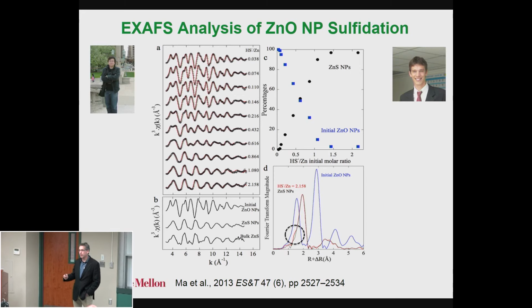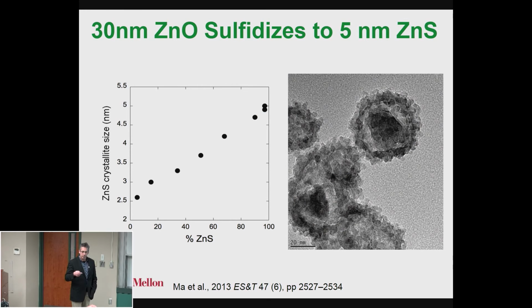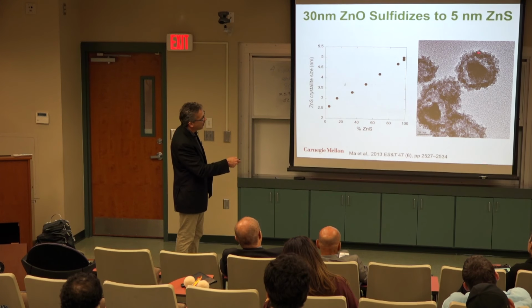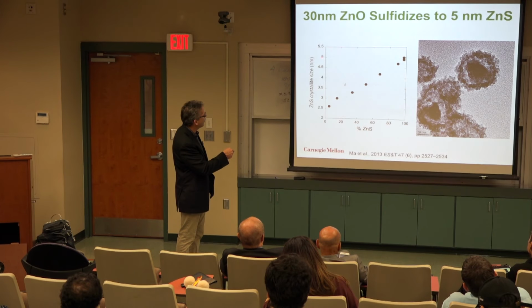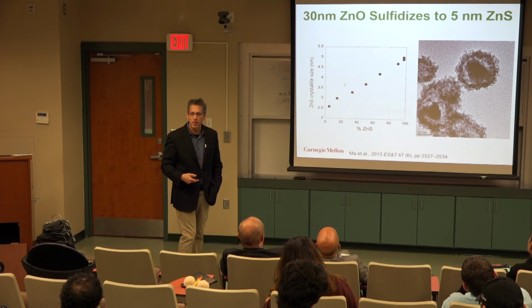So we use this spectroscopy to understand these materials and how they change. And we can analyze our spectra and say things like, what's the size? So this is my zinc oxide core. These are the crystals on the outside. These are zinc sulfide crystals, and this is a zinc oxide core. The size of those zinc sulfide crystals ranges from 2.5 to about 5 nanometers, depending on how much sulfur I put in. So I had this lovely zinc oxide particle that was being sulfidized and creating these little zinc sulfide crystals. So we can start to understand our system fully this way.